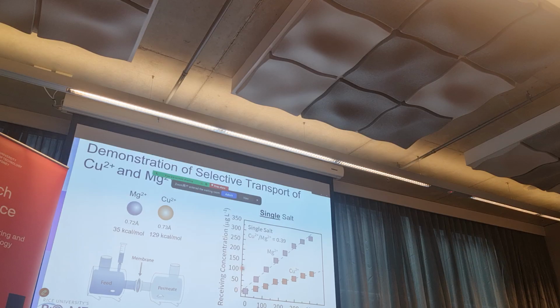But we see here that when you measure concentration versus time, for copper, the slope, which relates to the flux, is much lower than for magnesium. Because copper, in single salt experiments, binds more strongly to this iminodiacetate group, and it slows down, as opposed to magnesium, which doesn't bind.